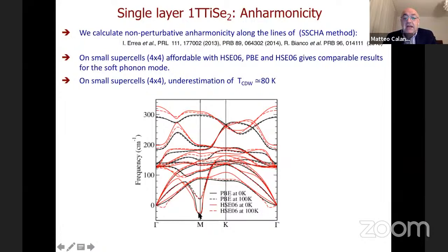And what you can see is that around 80 Kelvin, the anharmonic correction pushes up the imaginary phonon, and the phonon becomes unstable if you try to fit. Here I just put the temperature at 0 and 100 Kelvin. If you fit with more temperatures, you will see the instability occurs approximately at 80 Kelvin.